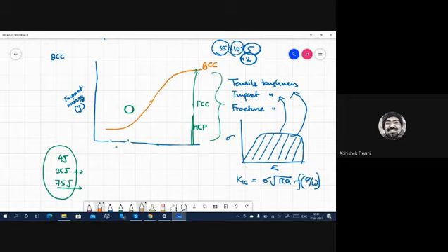So if I have this kind of curve, and on another axis, I can plot, so here I am plotting impact energy, and here I can plot the percentage of the area of the specimen which is flat or fibrous. So flat will be brittle and fibrous will be, so let me write it, fibrous. So fibrous area will represent the ductile fracture, and we will see what area looks fibrous after breaking the specimen.